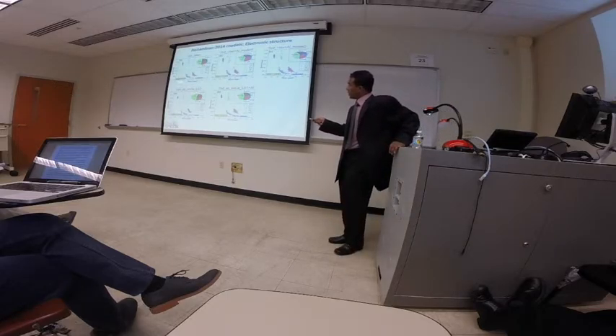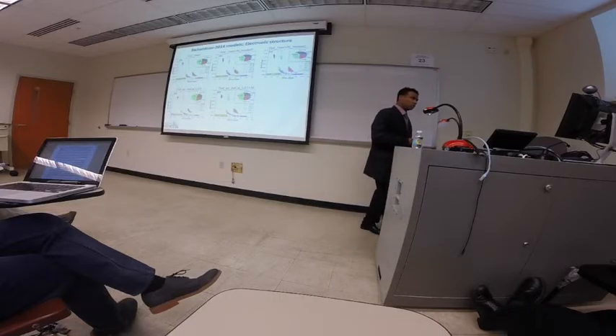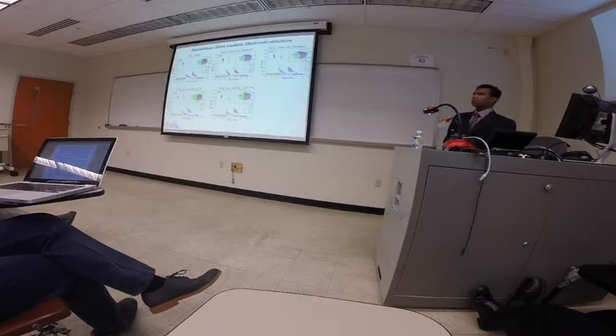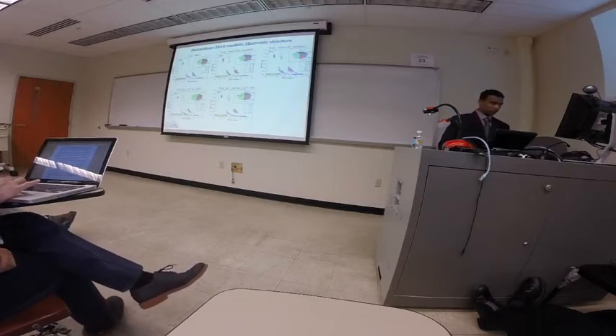And also, the highest total bond order density is this crystal, and the lowest one is this. So, cohesion-wise, the calcium atoms in the interlayer seem to play a significant role in CASH crystals.